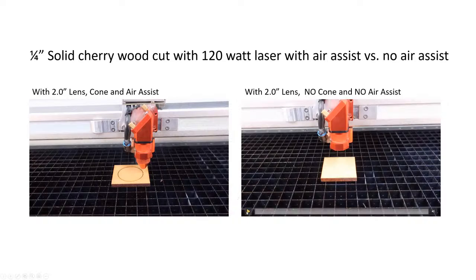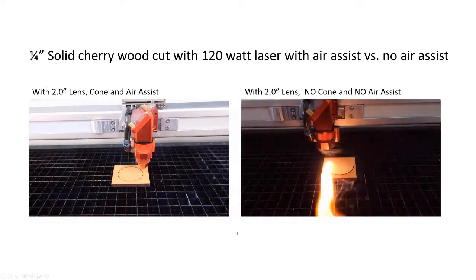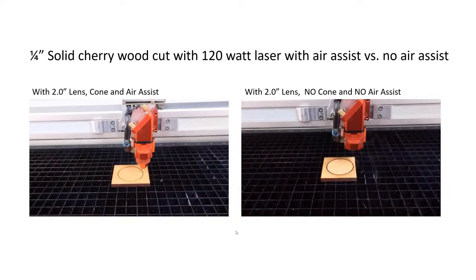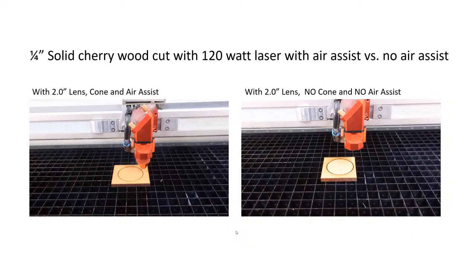Where if I run that same one with no cone, you can see the difference. You get this flat out flame. Just that small amount of flame you saw right there was the difference between the fact that I had to clean that lens after that. A 3-second cut and I pulled the lens out and it was hazed. There was a slight smoke haze on it.